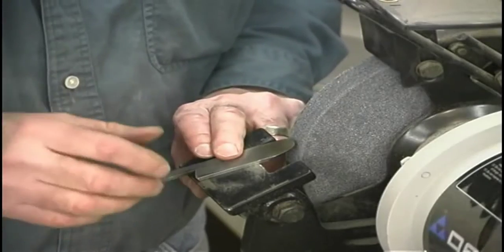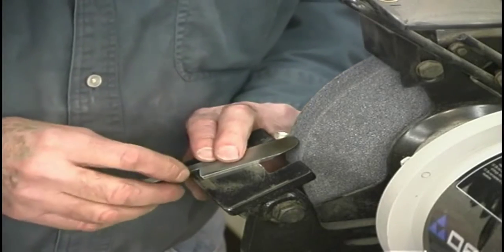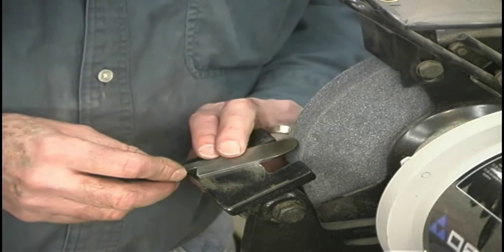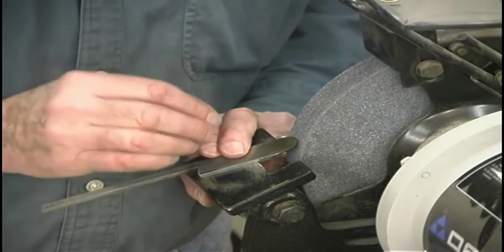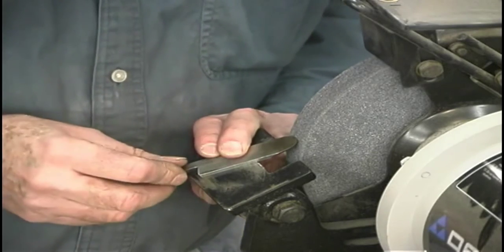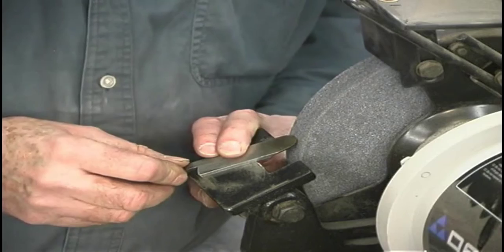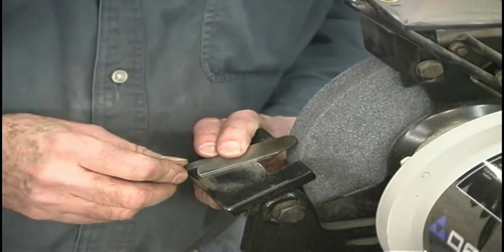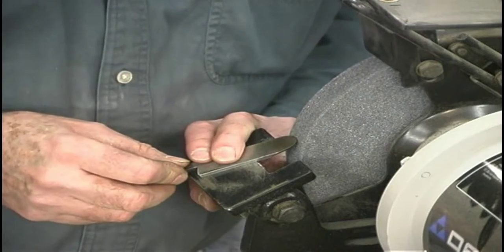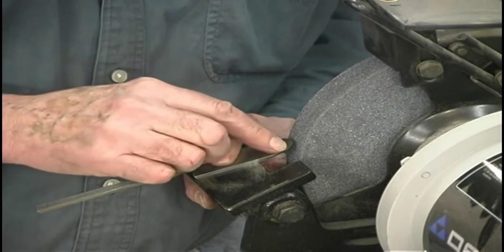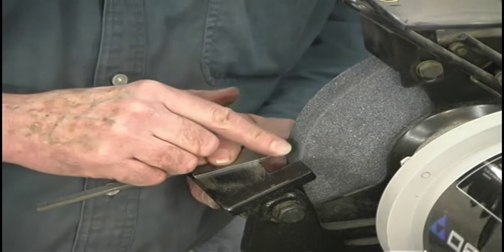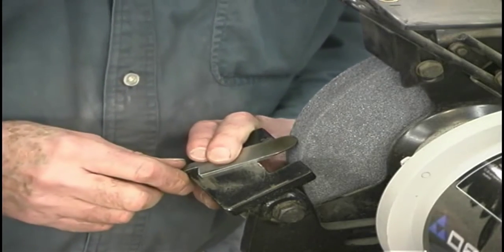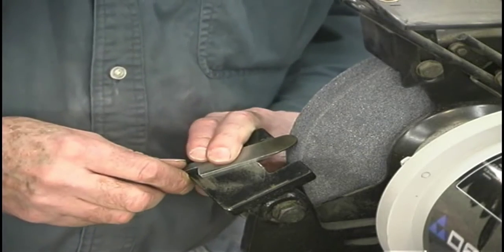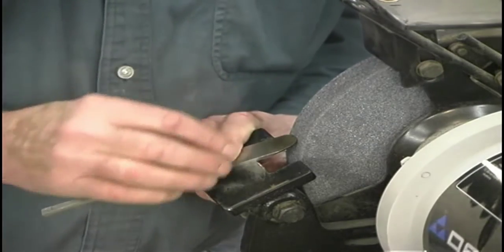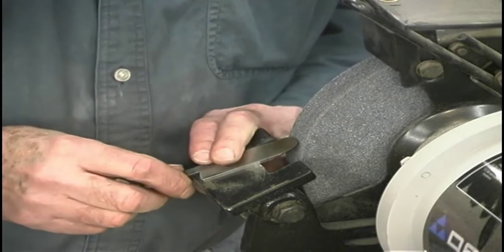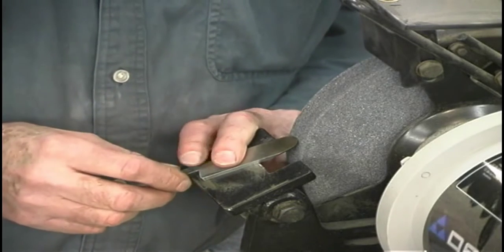Now, a word of caution about this grinding. You must remember that this is high carbon steel. This is not high speed steel. So you have to keep it cool. If you have a water cooled grinder, then you would have no problem at all. But if you're using an ordinary grinder, you have to be very, very careful. If you get any discoloration at the edge, any bluing in particular, you will have to stop and start all over, do the heating to the 1500 degrees, bright red, quenching and retempering, because you have taken all of the hardness out of it. So this is probably the most difficult or trickiest part of the whole operation.